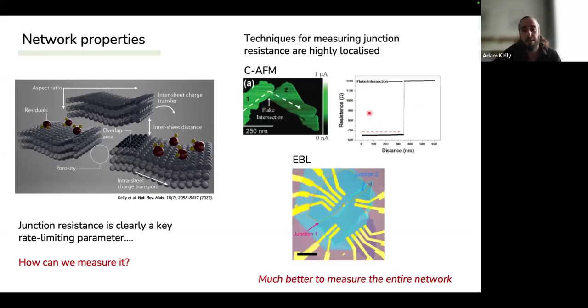Another way to do it is with EBL, where we take two nanosheets that are slightly overlapping, and we deposit electrodes on them, and we can measure the junction resistance across them, taking things like area into account. But the problem is, these are very highly localized techniques. If I have a device, an entire network, these are simply not feasible. So we need a way to measure an entire network really quickly.